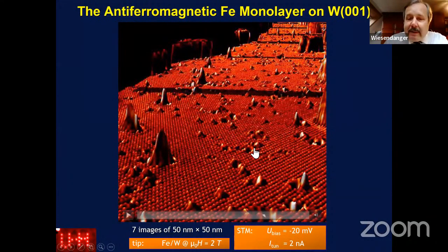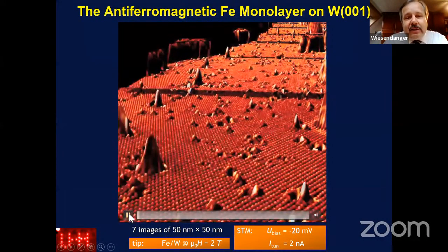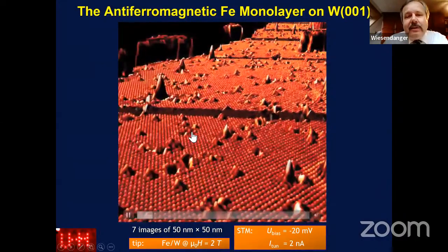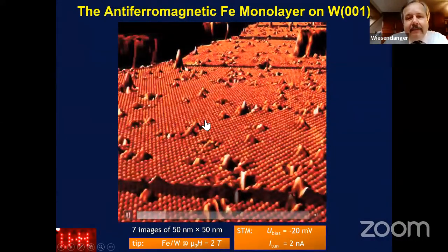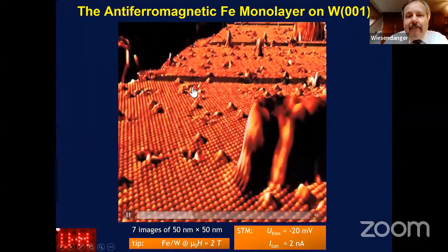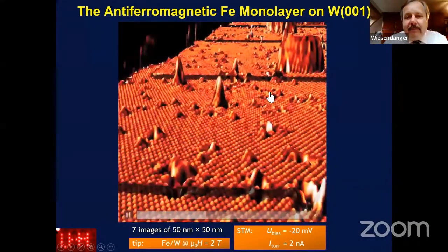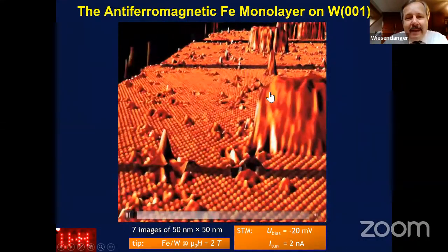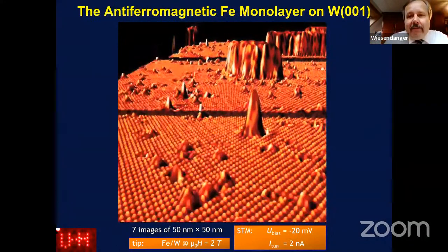And we see also typically all kinds of defects on the surface. We see natural defects, we see single atoms, iron clusters here, and also single atomic layers of iron islands here. And we can create some simulations of a flight over such a surface. And you see very nicely the spatial coherence of this antiferromagnetic lattice, though you have all kinds of defects present, but these defects do not harm this coherent antiferromagnetic lattice.